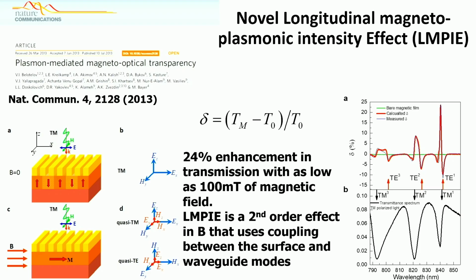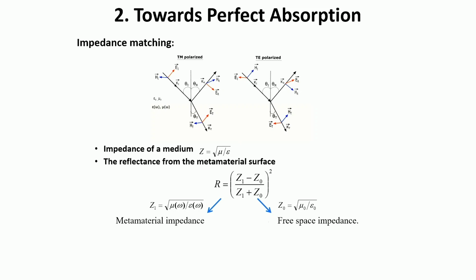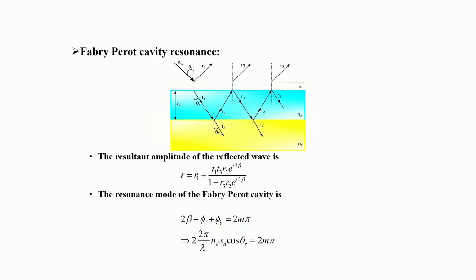Right? So now, take an example of perfect absorption. Most of us want our detectors or photovoltaics to have almost all the incident light absorbed. One of the basic criteria for near 100% absorption is to reduce the reflection, so we need impedance matching at the top, Z1 equal to Z0, so that the reflection goes to 0. And eventually if the transmission is also suppressed, we can have near 100% absorption in these structures.